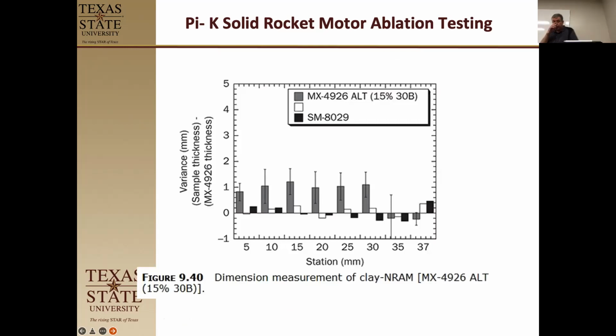Okay, so what I saw here, and this is what they're doing, is they're looking at the sample thickness as a dimension from the center. No, from the outside edge. So they're starting at the outside edge and going into where the hole is, where the nozzle is. And they see that the sample thickness actually went up here. Why did it go up? Foaming. So we had foaming, and it didn't get ablated off much either. So we see expansion on these.